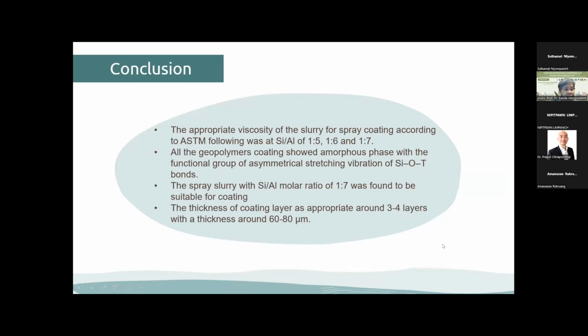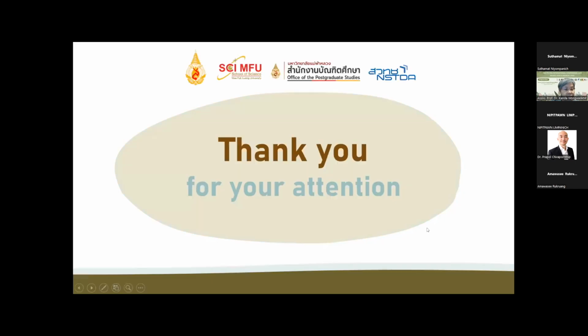In conclusion, the appropriate viscosity of the slurry for spray coating according to ASTM was at silicon to aluminum molar ratios of 1:5, 1:6, and 1:7. All of the geopolymer coatings showed the amorphous phase with the functional group of the symmetrical and asymmetric stretching vibration of the silicon-oxygen-T bond. The spray coating, especially with a silicon to aluminum molar ratio of 1:7, was found to be suitable, and the appropriate coating thickness was around 3 to 4 layers, with a thickness of around 60 to 80 micrometers. Thank you for your attention.